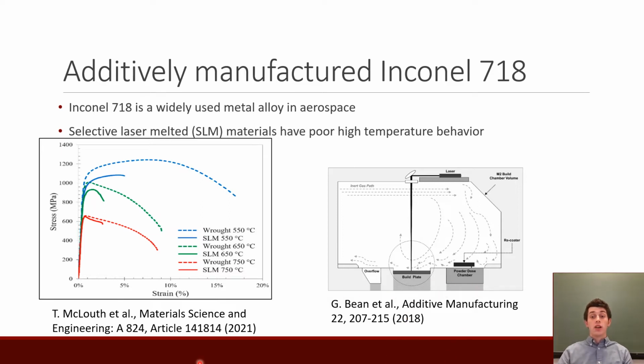Additive manufacturing makes manufacturing metals easier and faster. In addition, compared to traditional metal manufacturing methods used in the aerospace industry, additive manufacturing can reduce waste material by up to 90%. Selective laser melted samples of Inconel 718 have shown similar behavior to traditional wrought samples at room temperature. However, tests have shown that the selective laser melted sample performs poorly at high temperatures. This is particularly apparent in creep, high temperature tensile, and notch resistance tests.